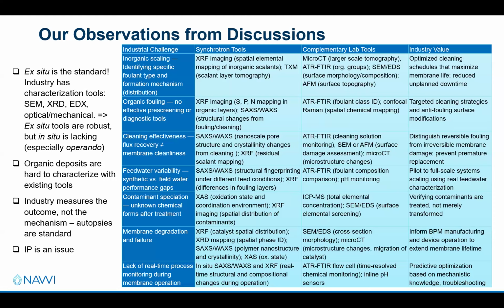Oftentimes when materials are cleaned, you say, okay, the flux is recovered, and so the membrane was cleaned effectively. But that's not necessarily the case, because you could imagine that some species are being trapped within your polymer matrix. So you still have some other species in there after treatment, but it looks like the flux is recovered because possibly the polymer material changed as a result of that.